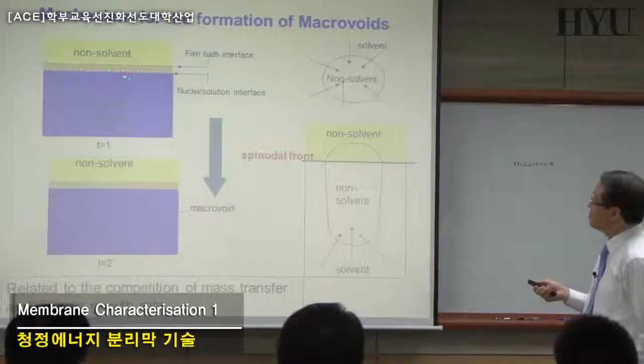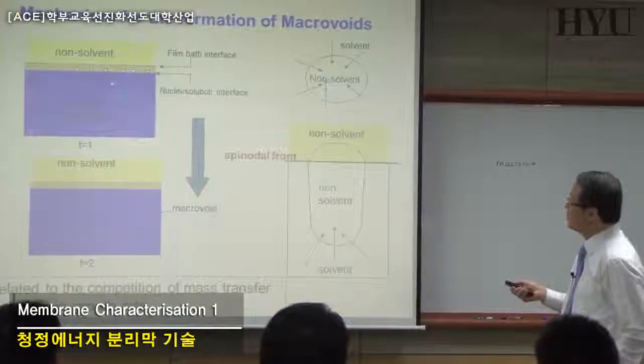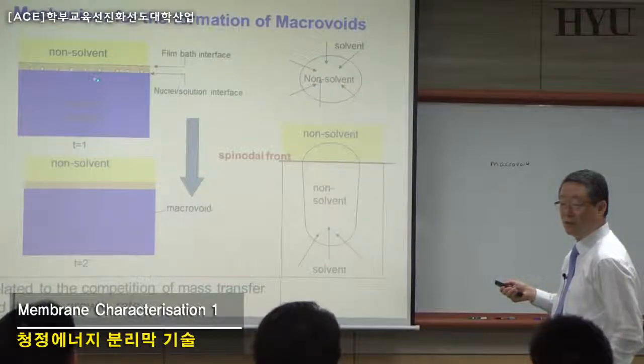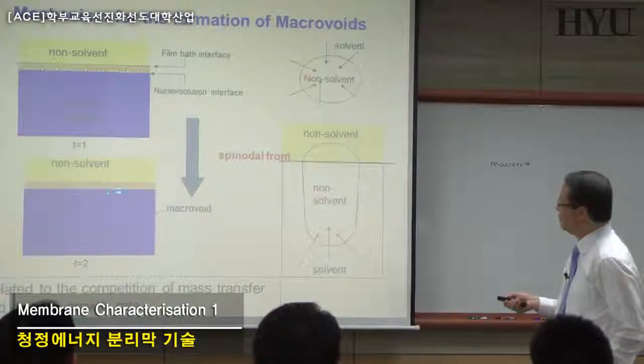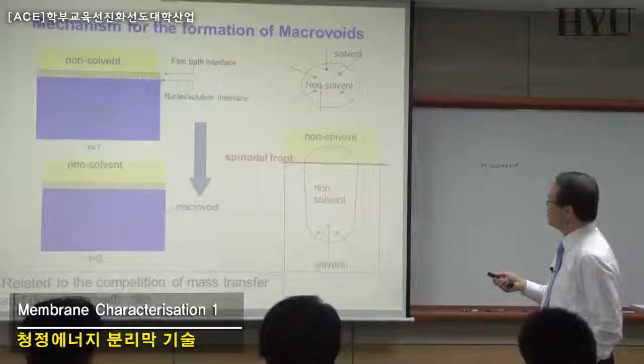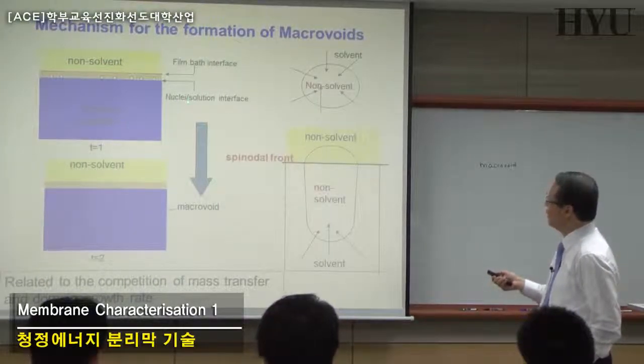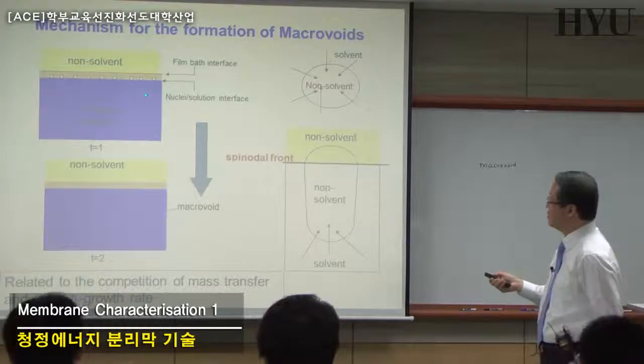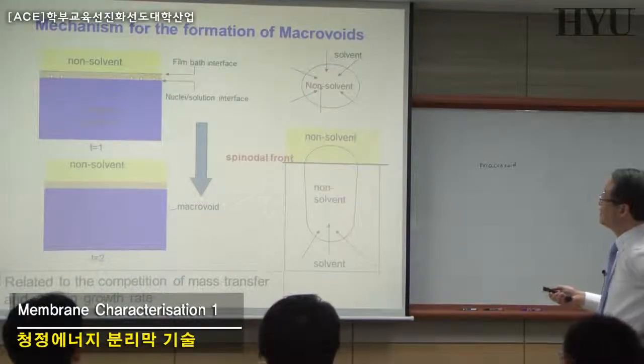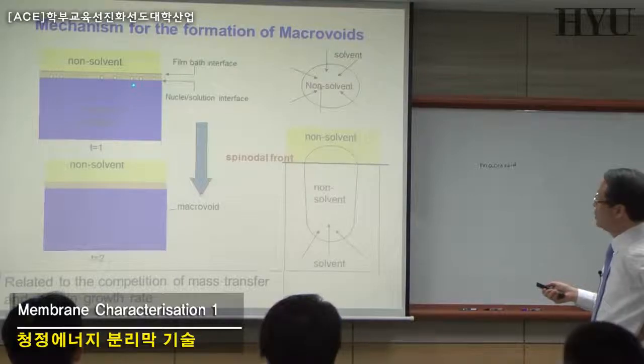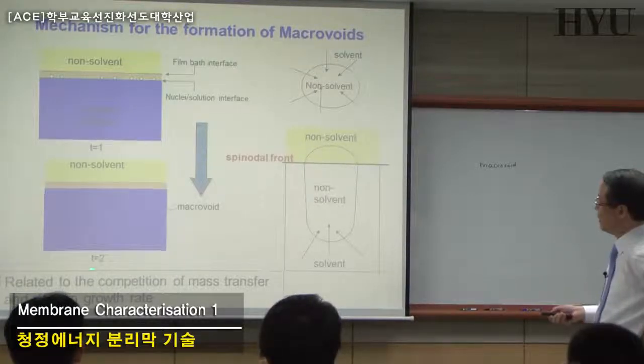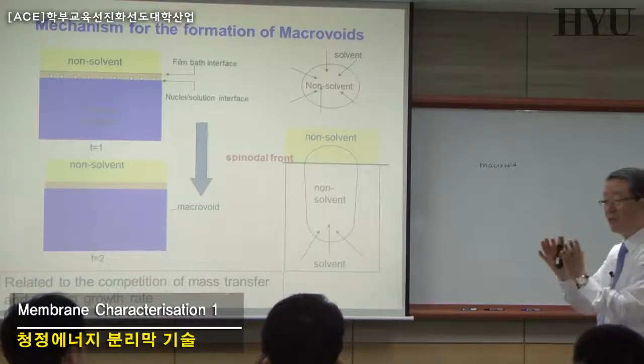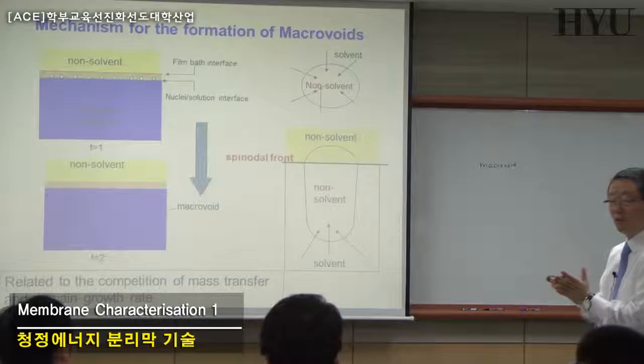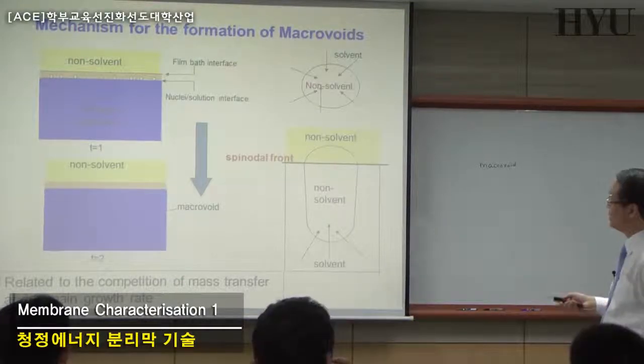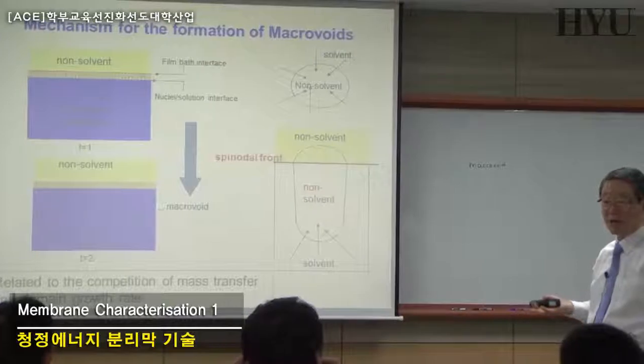Now, in this case, the solvent should go into this non-solvent cage, and so in this case you have the non-solvent intruded again and again, and as a function of time, this small cage will start to grow, and at final time from T1 to T2, you can have a growth of your macro void. That way you can form the macro voids. And this is the kinetic factor because this is really with the time. Okay?